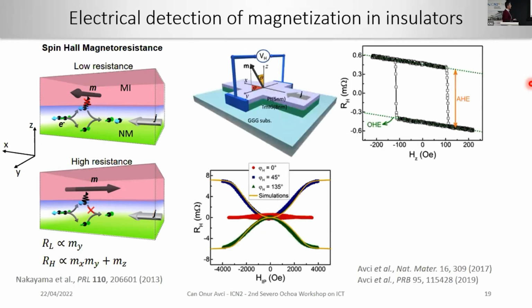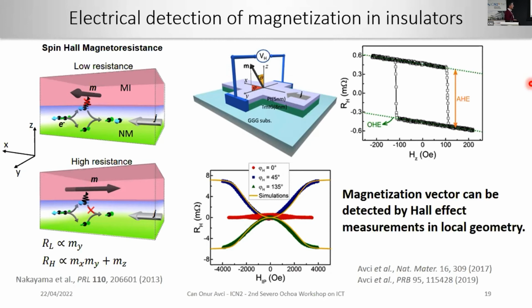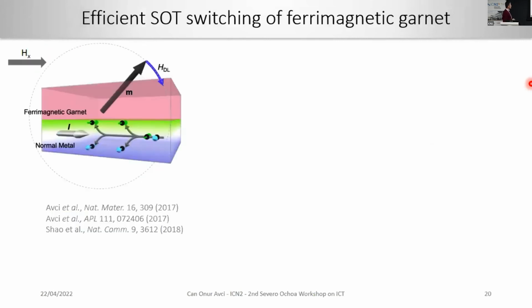And this Hall effect signal can be nicely measured in devices that look like this. So you only have current going through platinum, but then you can nicely probe the out-of-plane magnetization. You can get the out-of-plane hysteresis by using an out-of-plane field sweep, or you can do an in-plane field sweep to get this coherent rotation of the magnetization. So in a local geometry, this is a very powerful technique to measure the magnetization.